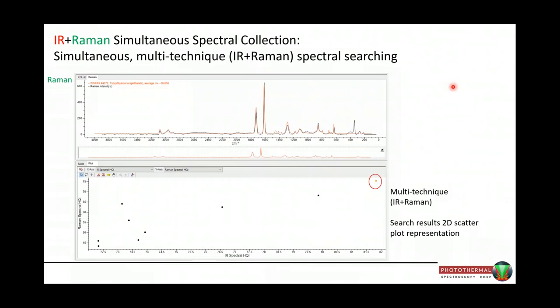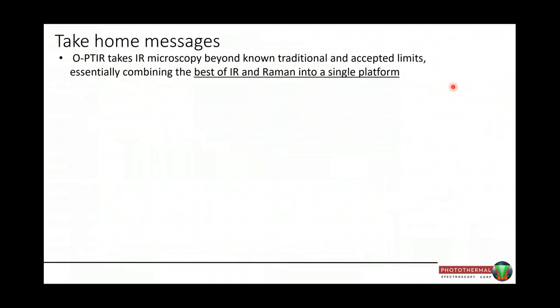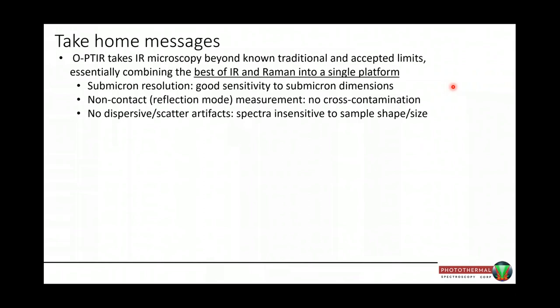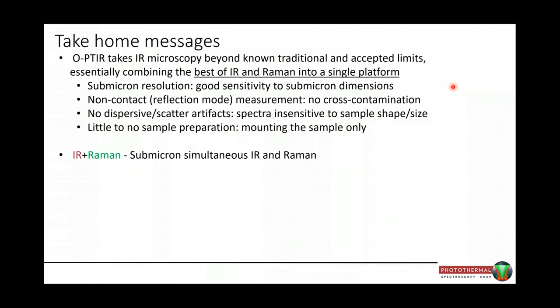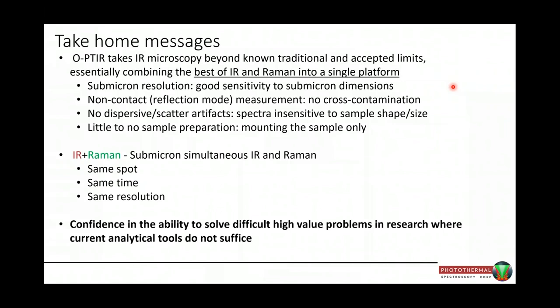So the take-home messages here are that OPTIR takes IR microscopy beyond traditional and accepted limits, essentially combining the best of IR and Raman into a single platform for sub-micron spatial resolution. It's a non-contact reflection measurement with no cross-contamination, no dispersive scatter artifacts, and the spectra are insensitive to sample shape and size. Little or no sample preparation. All you have to do is mount the sample. And then by combining with Raman, we can get simultaneous submicron IR and Raman at the same spot, the same time, and the same resolution, which gives you confidence in the ability to solve difficult high-value problems in research where current analytical tools may not do the job.